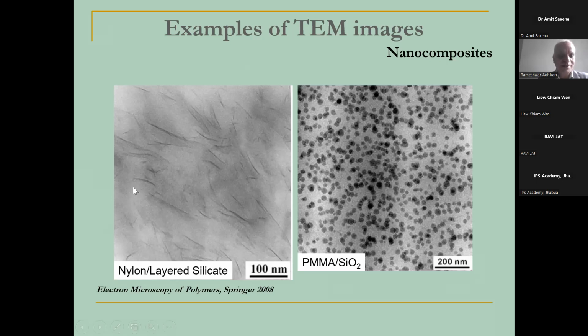So therefore, these layer structures, the darker lines, are the areas of the layered silicate having the higher densities, which is able to scatter more and more electrons. And the brighter areas here are occupied by nylon. In the same way, in the right images, you can also have a look at the scale bar. This scale means this length is 200 nanometer. The brighter areas are the relatively low scattering plexiglass, PMMA, polymethyl methacrylate polymer, and the darker areas represent, of course, the silica, by virtue of their higher densities and their ability to scatter more and more electrons.